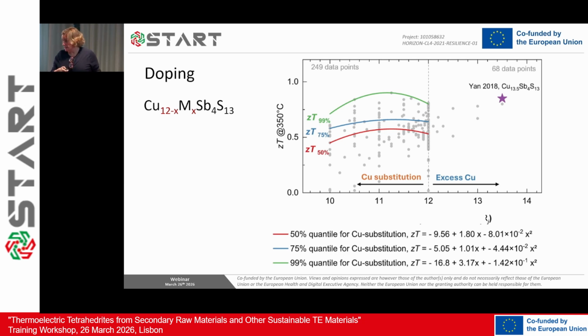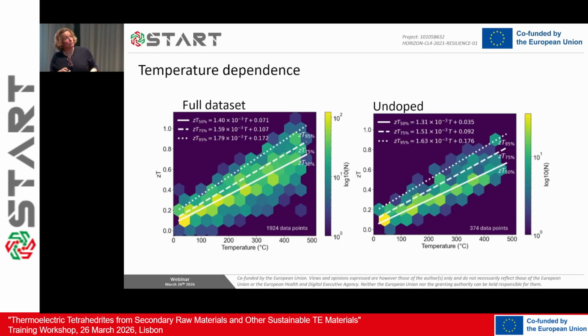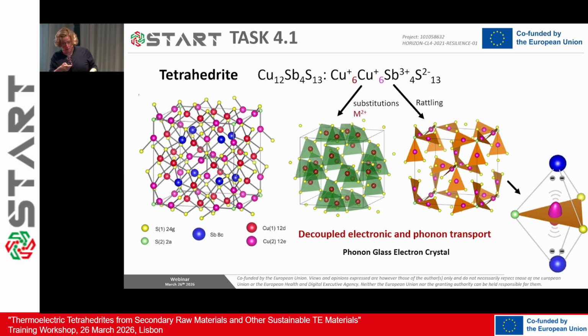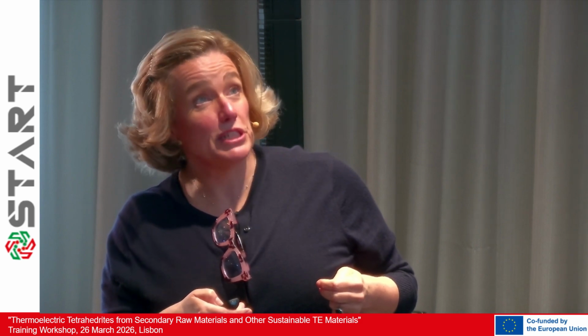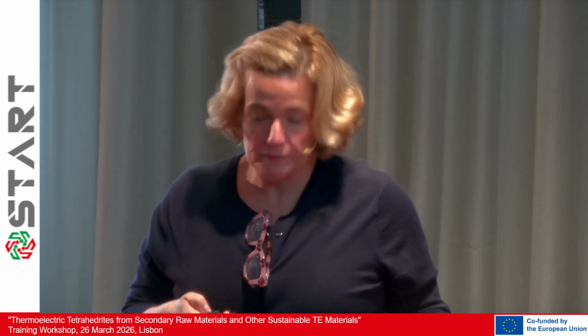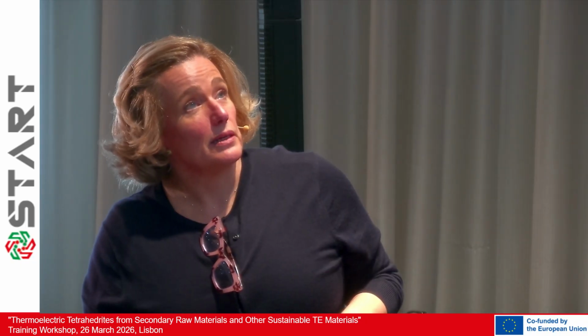And this makes sense, because what happens—I have to go back to show something I forgot to mention—is that since we are replacing copper, which is believed to be in a 1+ state, with 3D metals, which are typically in a 2+ state, you can never really replace all the coppers. The maximum you can replace is 2 coppers, because otherwise it becomes resistive, or it's not stable, which is what happens in some cases.